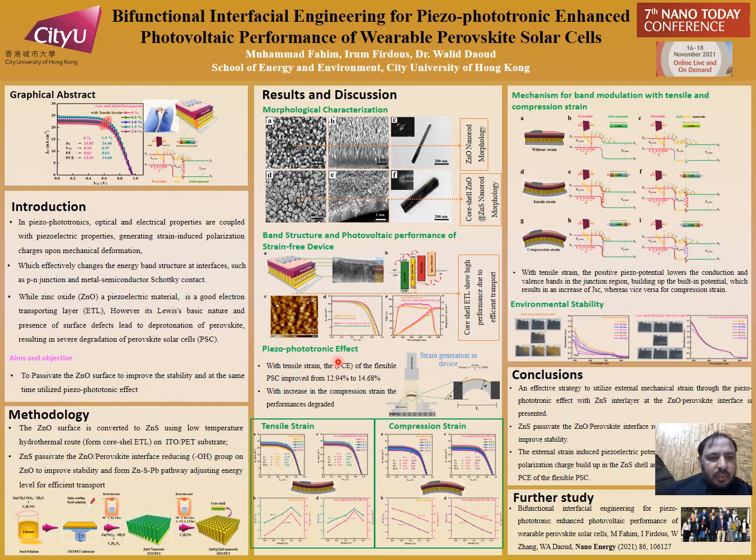Meanwhile, the piezotronic behavior is utilized by applying mechanical deformation on the flexible device, which improves the efficiency from 12.94% to 14.68% under tensile strain. The mechanism has also been introduced, showing that reducing the hydroxyl groups can improve environmental stability as well.